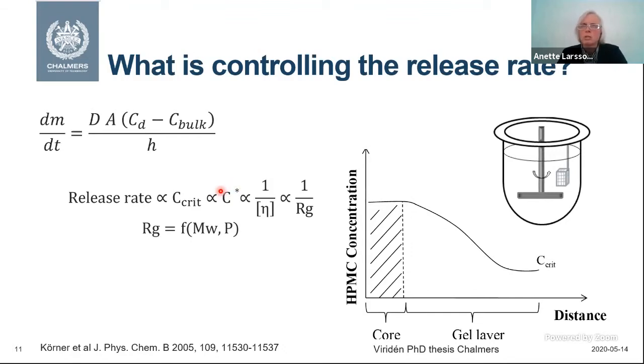And the overlap concentration, for an entangled polymer solution, is the concentration where polymers are entangled, but when you dilute them, water penetrates into the gel more, and they come more and more far from each other. Then they will reach a point where they are separate and have no contact with each other. That point, where they lose contact with each other, is the overlap concentration. And that depends on the size of the polymer chains, which can be described with the radius of gyration. And we know that the radius of gyration is a function of the molecular weight and the persistence length.